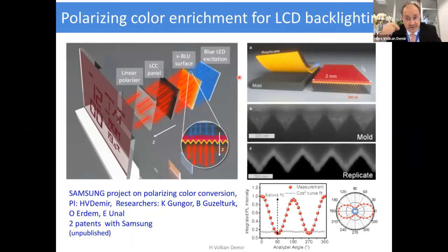You can do it for outdoors, specifically tuned. Again, this is possible because we have sharp emitters, but if you wish, you can use this also for example, liquid crystal display backlighting. And this is a project indeed directly funded by Samsung, where we had two projects in a row. And this was not only for color conversion purposes to have enrichment of the color span you can create on a TV screen, but also at the same time to have polarization control. So normally in a liquid crystal device, you need polarized light illumination, but typically you would start, for example, using LEDs or in old days fluorescent lamps, unpolarized light. So you immediately waste at least half of the photons.